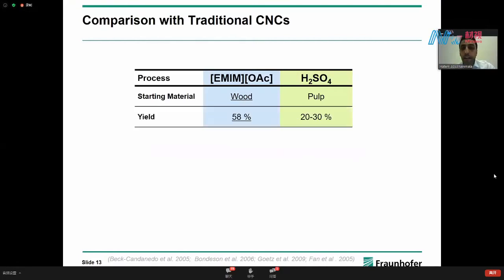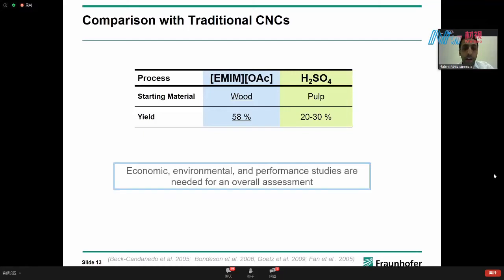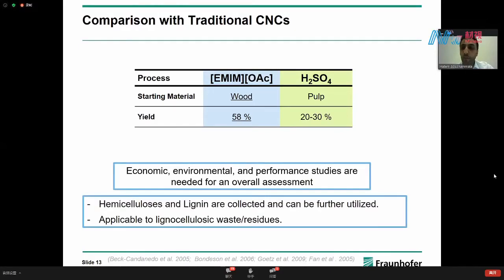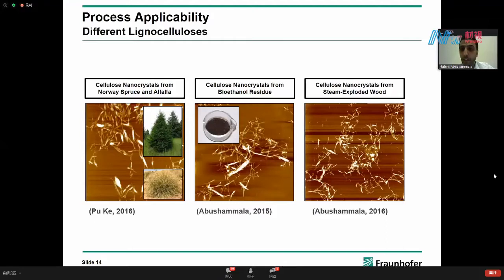Now, this process has the advantage over the traditional sulfuric acid process that starts with pulp. In terms of yield, we can get like 2 to 3 times the yield we get from the standard process. But obviously, a more thorough assessment of such processes will be needed. What's also interesting is that the hemicelluloses and lignin from this process, you can collect them and fractionate them easily, and you can use them for making other biomaterials. It's also applicable to different lignocellulosic waste and residues, which was actually the case here. I applied my process to different lignocellulosic residues from different industries, and it was always working very nicely.